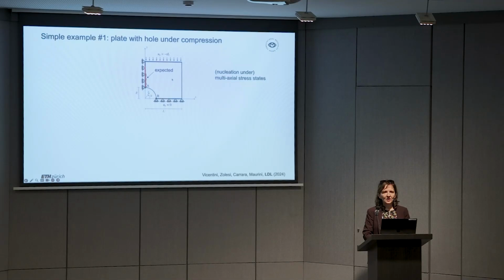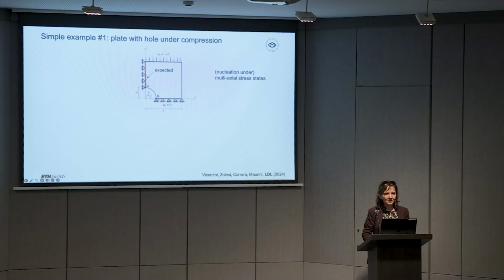So imagine you have a plate with a hole and you want to compress it. If it's in tension, everything will be perfect. But the issues start when you have compression, or also in shear cases. So let's look at this example. Of course, due to symmetry, I'm only studying a quarter with symmetry boundary conditions. When you compress this plate, what you expect, and you see this in experiments, is a splitting crack. So you expect the crack to start from this point and propagate upwards. Essentially here you have a tensile stress at this point, and you also have a compressive stress at this point, and so there's a competition, let's say, between nucleation in tension and nucleation in compression, right? Because you can also nucleate cracks in compression.